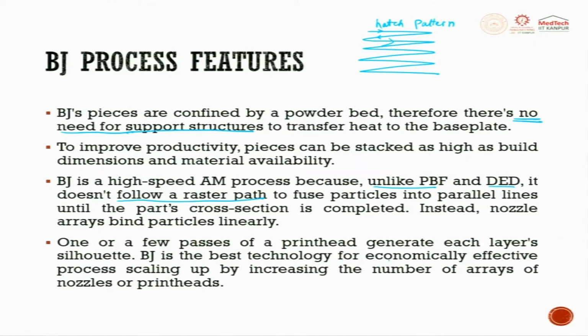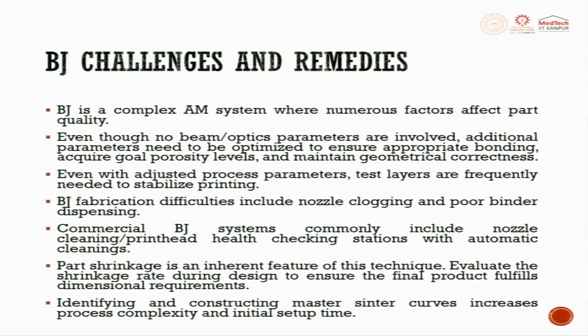Binder jet is the best technology for an economically effective process, scaling up by increasing the number of nozzle arrays or print heads. So, what are the big challenges? Though it is very economical and very fast, there are still a lot of challenges and remedies. It is a complex AM system where numerous factors affect the quality: viscosity, powder, all these things. Even though no beam optical parameters are involved, additional parameters need to be optimized to ensure appropriate bonding, achieve the goal porosity level, and maintain geometrical correctness. Even with adjusted process parameters, test layers are frequently needed to stabilize the printing.